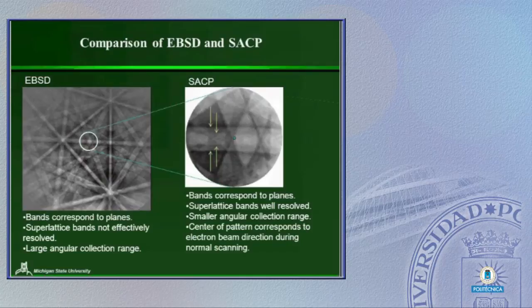If we compare that to a selected area channeling pattern, here we actually collect a much smaller area. Now we can directly compare these two, but now we're collecting information from maybe 5 degrees. And so that makes it more difficult to determine exact orientations because we don't have all this broad information. On the other hand, we can see fine details. For example, these lines here are superlattice bands, which don't show up in these other two patterns. This happens to be a 1-1-1 axis in titanium aluminum. And now the center of this pattern, again, corresponds to the electron beam direction during normal scanning. And that's what makes them very useful for us.